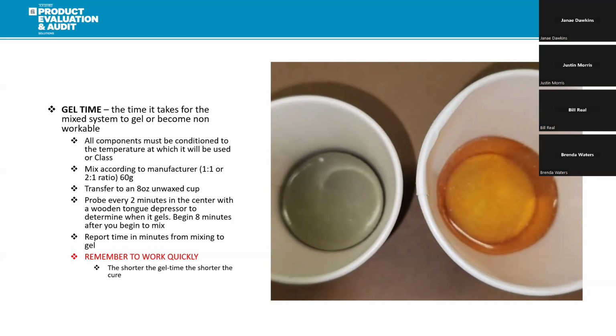So you want to look at the time from when you mix until the time it gels, and report the time in minutes from mixing to gel. But I have to remind you, if you're performing this test in your labs, you have to work quickly because the shorter the gel time, the shorter the cure. So you want to be careful that you stay right there when you're performing gel time.